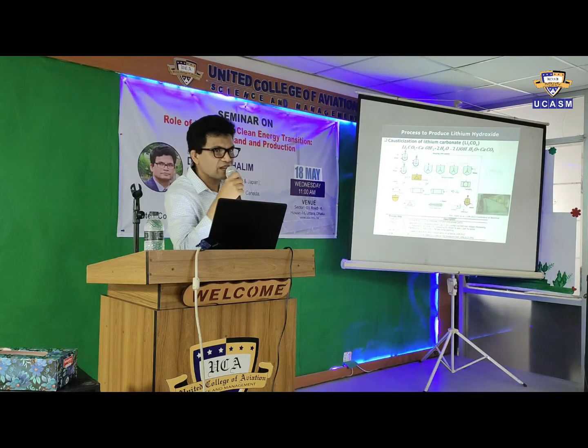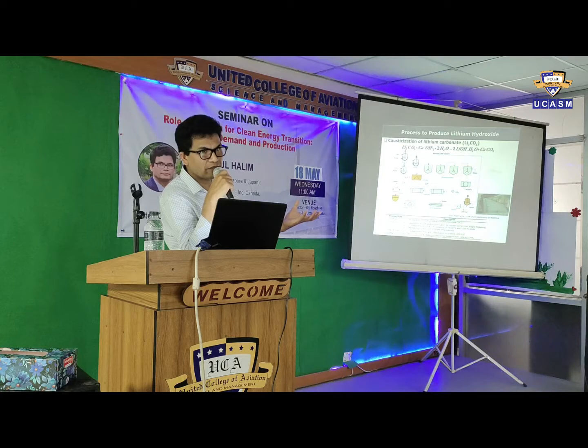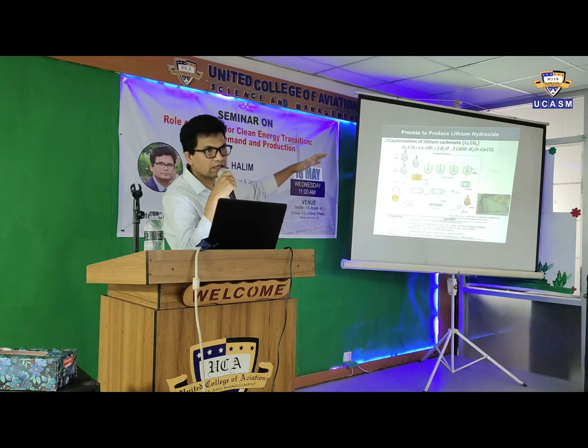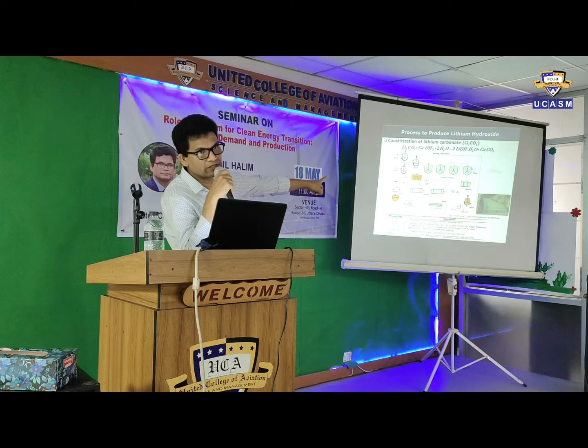The calcium carbonate has very, very low solubility, so it reports to the solid, and the lithium hydroxide has a high solubility and is in a liquid form. This is the process they are using in the industry to make lithium hydroxide. But this process is not very efficient. There is a significant loss of this critical metal to the calcium carbonate.